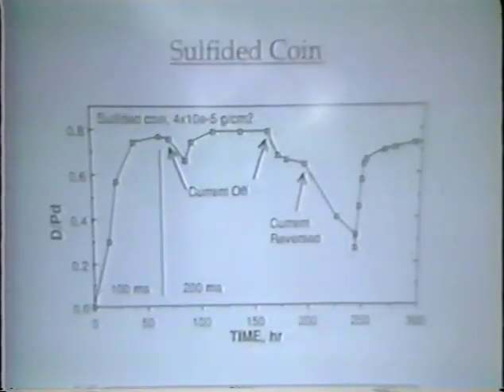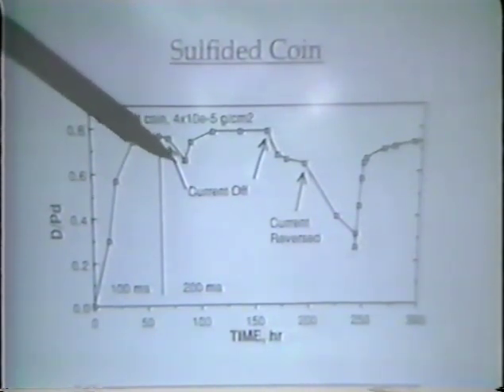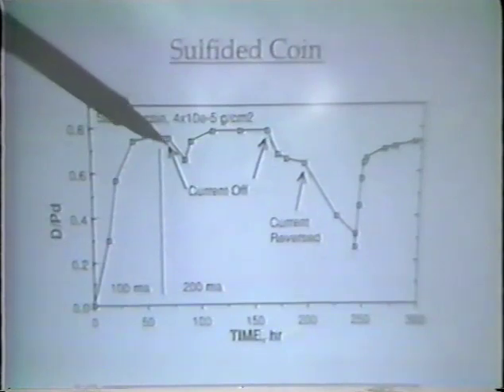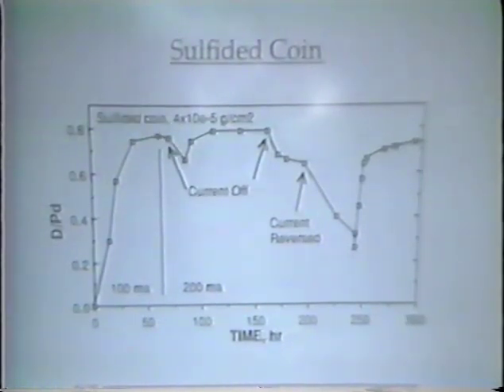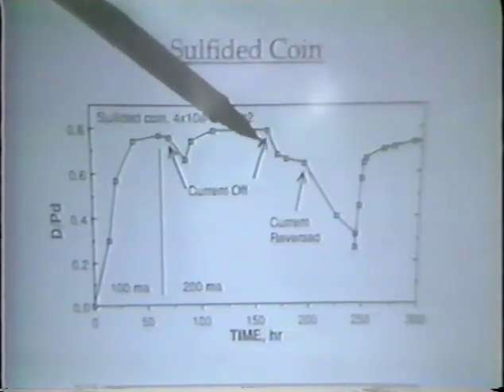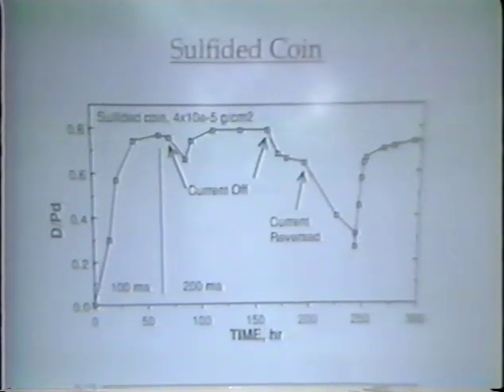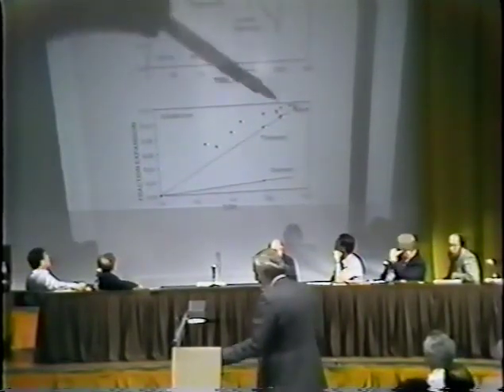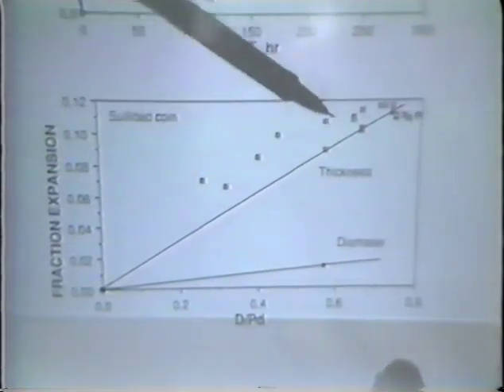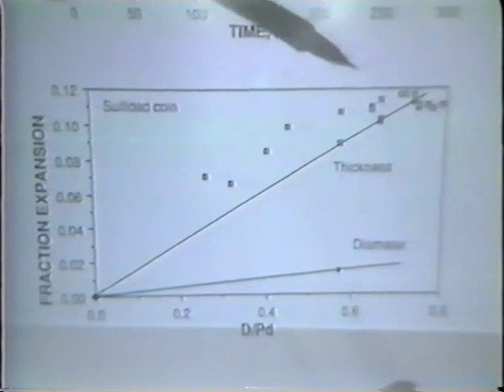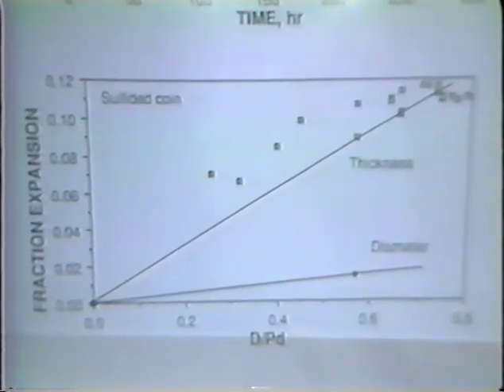The material took up hydrogen very nicely, came up to very near 0.8, about 0.78. The current was turned off and it decayed down. We noticed that if it's well poisoned like this, it doesn't decay down quite as rapidly as it would if it were a clean surface. We tried the current reversal technique on it, and it never did come back up to where it was. But you'll notice that the thickness also does not come back down the same line. When you do a current reversal, take the hydrogen back out, you have a residual expansion.